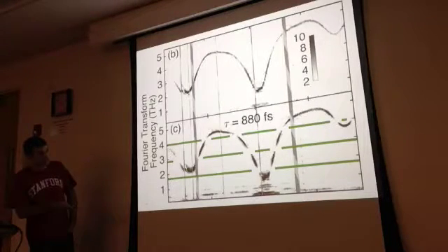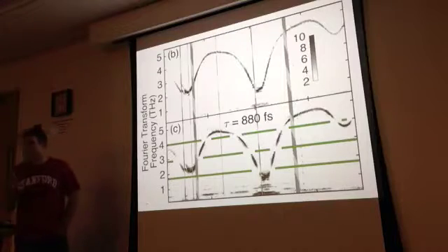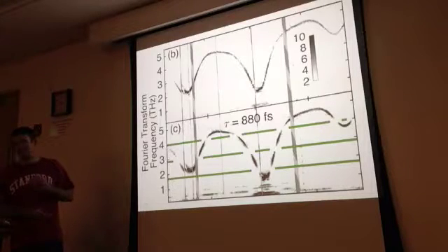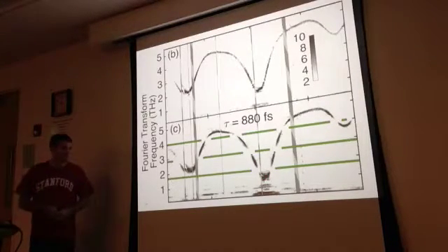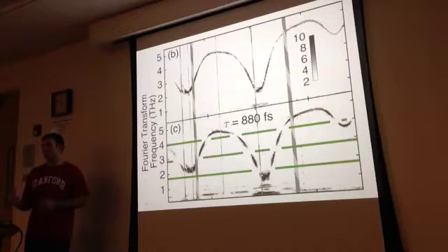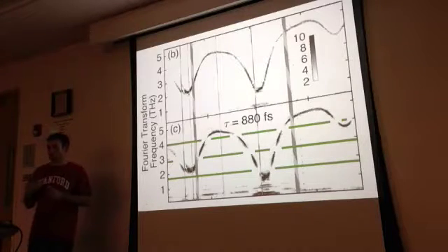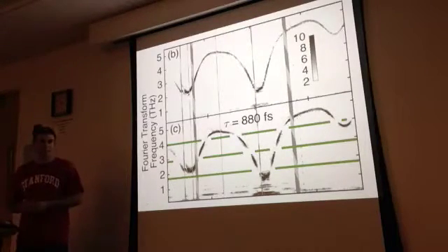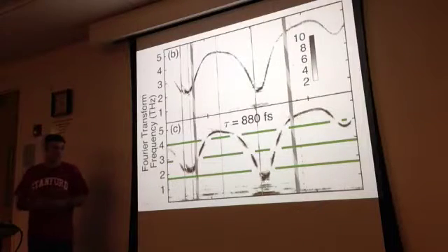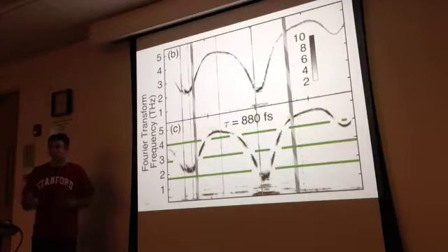And what you can see is that these frequencies, the ones we expect to be stopped by the second pulse if we're actually getting squeezing, it does appear that the second pulse is stopping the oscillations because we see an obvious lack of signal at these frequencies. So, yeah, this indicates that the way we're coupling to these high wave vector phonons with the short wave vector light is actually by changing the interatomic force constants. And this is nice because it's kind of a general purpose thing, I mean, you can always expect that you'll be able to change the force constants. So there's a lot of reason to believe that we'll be able to use this technique on a vast array of different materials.